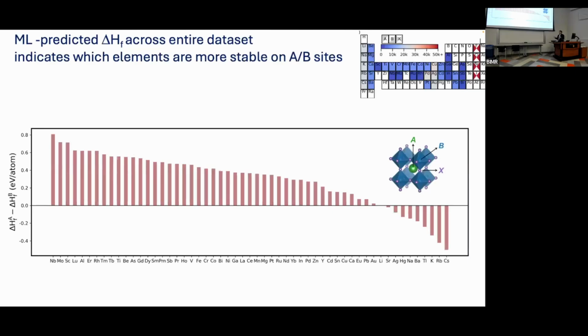Having a large data set, we can also analyze what the right element combinations are that form stable materials. So which elements prefer which sites, basically. In this case, this is the difference of the energy aggregated over the entire data set between if an element is on the A site versus the B site. So we just calculate, for all the structures that are available with those two elements, what is the difference in their energy on average. And we can see some elements strongly prefer, so this is a negative value, so this value is much more stable, strongly prefer being on the A site.